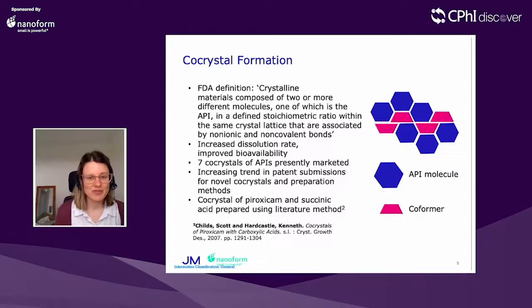In terms of the prevalence of co-crystals, there are actually already 7 co-crystals presently marketed, but this is definitely an increasing area of interest. We can see this with patent submissions, both for novel co-crystals and also preparation methods for co-crystals, which has increased a lot in the last few years. In this study, again, we formed a co-crystal of piroxicam using a literature method, and here succinic acid was used as a co-former.